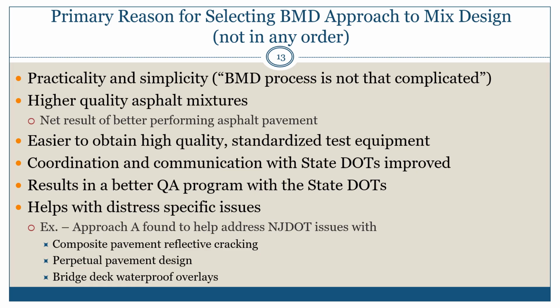They think that that will improve as there's a learning curve that both the agency and industry are going to have to work around. They also feel that the results in a QA program are going to be better because now there's a performance criteria attached. And they also think that moving to a balanced mix design approach is going to help with specific distresses. An approach, for example, in New Jersey, we found that it was used quite successfully to help mitigate reflective cracking. We could utilize it in developing better mixes for perpetual pavement and even design specialty mixes for bridge deck waterproof overlay.